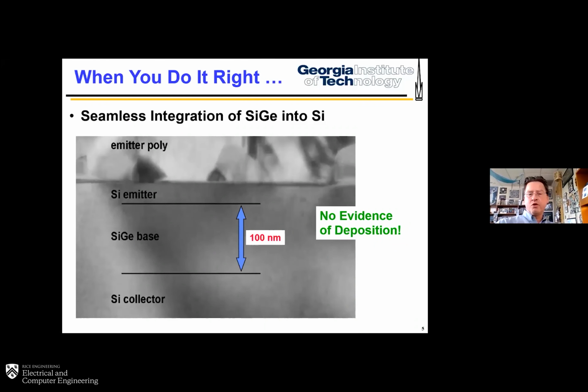So when you figure out how to do this right, you introduce the silicon germanium alloy inside the silicon matrix. It's done in a pure silicon manufacturing fabrication facility. All it takes is a silicon germanium epi tool. And if you, in this case, take a detailed cross-sectional TEM image of that, you see that there really is no evidence that silicon germanium is even there. And so no obvious defect formation or yield detraction or anything that makes that difficult from a fabrication standpoint. So silicon germanium bipolars really are silicon technology, and I think that's absolutely essential to the way it's practiced in 2020.